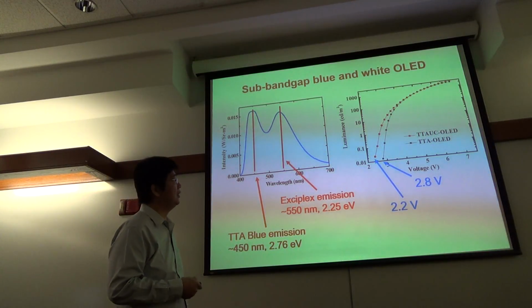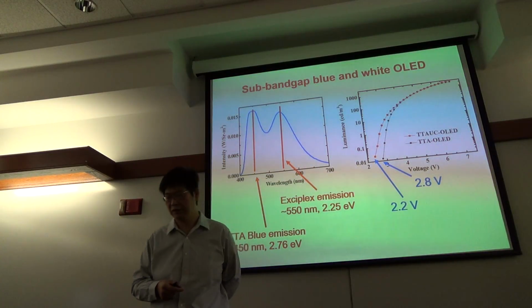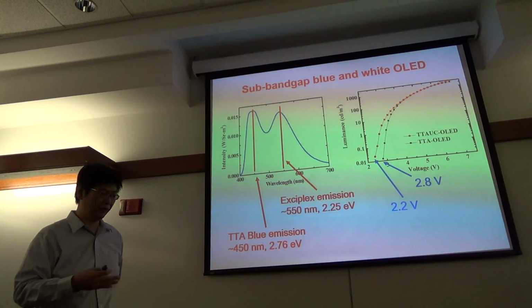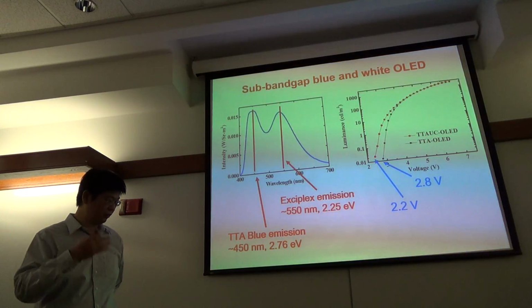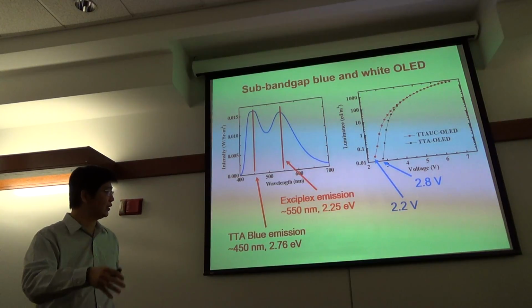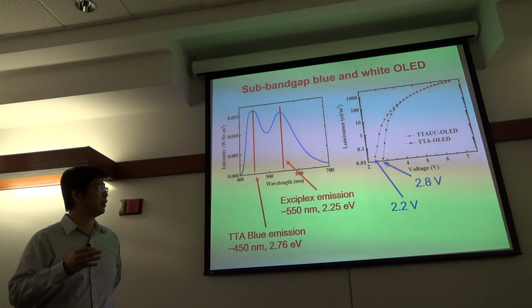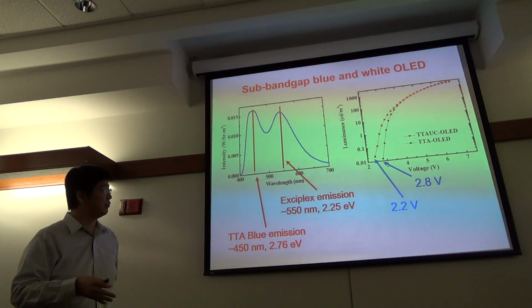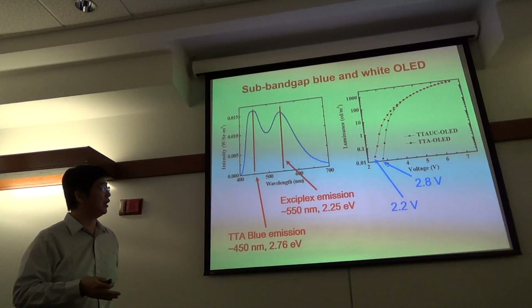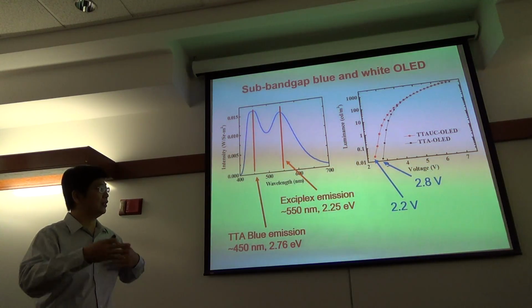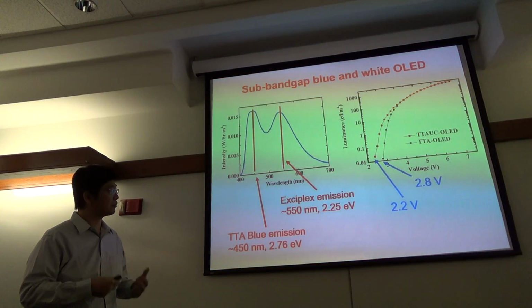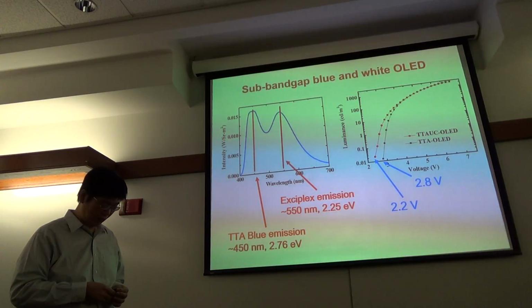The other thing is, as we know, for the LED and OLED it's similar, but for the LED, red, green, blue, the blue one has a longer lifetime, but the green one has the shorter lifetime. But for the OLED, it's different, because for the organic material, if the wavelength is shorter, the energy is larger, so that will reduce the lifetime.